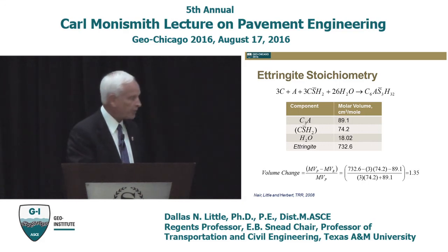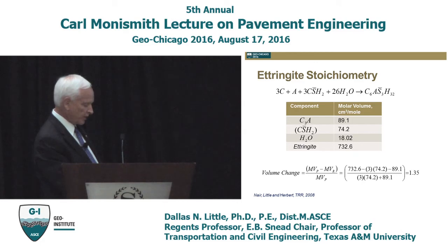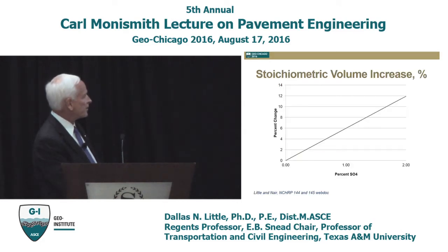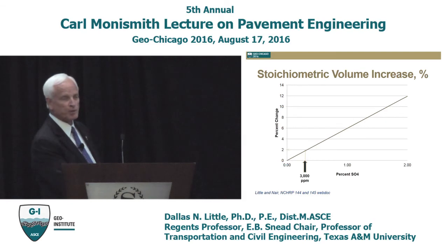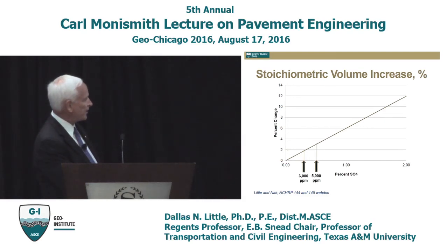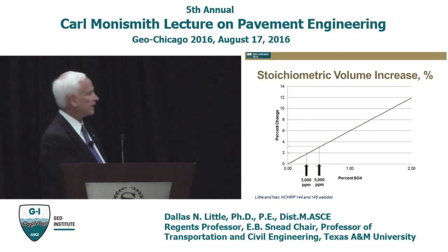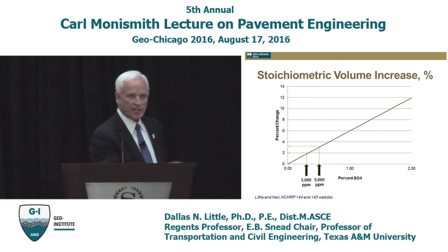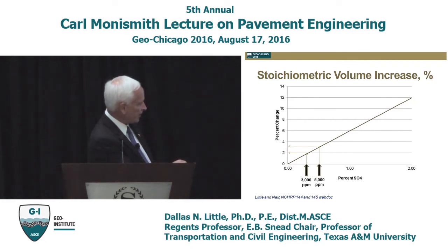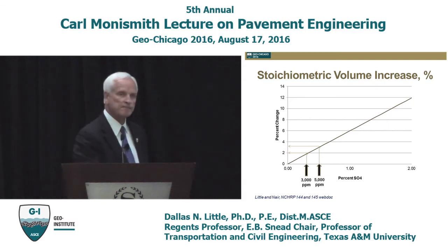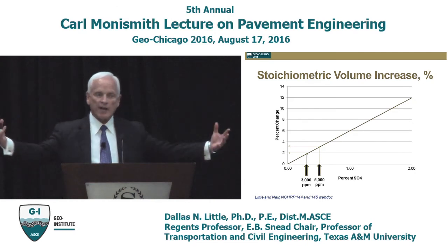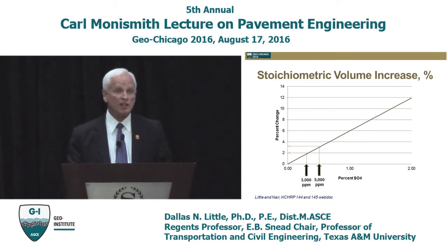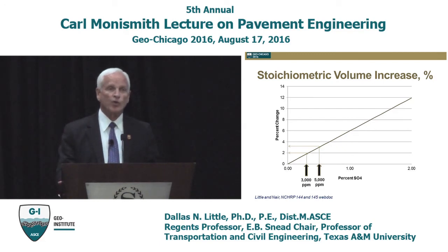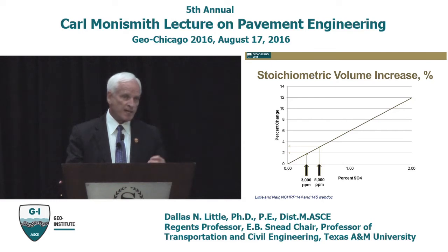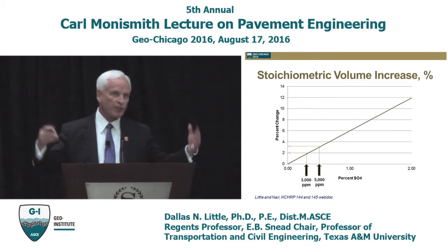Okay? So that's where you come in with the stoichiometrics, and using that, you can easily come up with a percent change. If you have 3,000 parts per million, then the volume change is going to be a little bit less than 2%. If you have up to 5,000 parts per million, then the volume change is going to be around 3%. And based upon many other aspects of our study, we found that if you develop this 3,000 parts per million and don't allow any more sulfate to come in from the outside, then you're pretty safe, because those sulfates tend to fill the voids, but really don't give you too much trouble if you keep mobile sulfates from coming in from the outside.